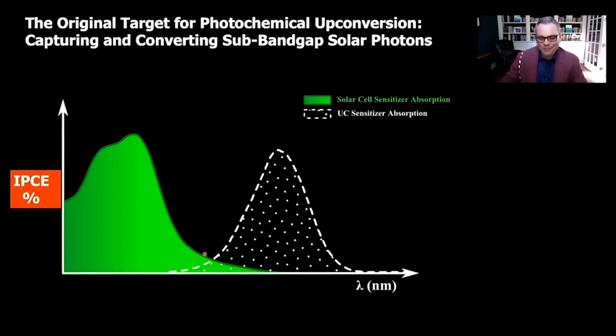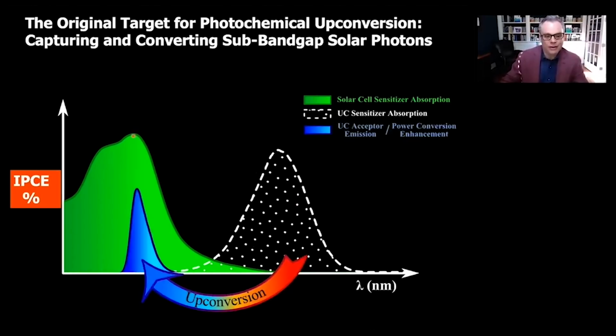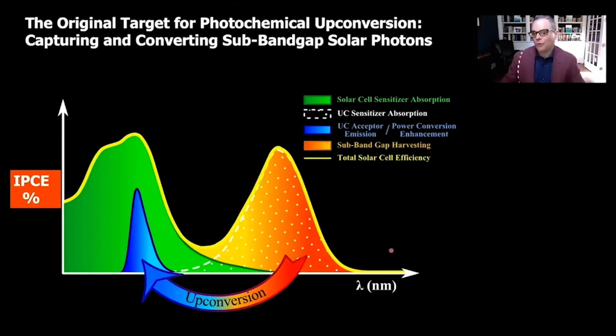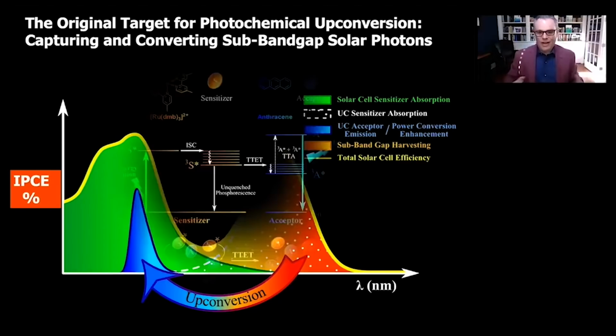So we had this idea, and we never really explored this in a lot of detail. Tim Schmidt has done this really beautifully, so has Ken Hansen. But what we thought at the time was, what if we have a sensitizer that can sensitize the dye-sensitized solar cell? If it has this absorption, and we can induce luminescence into the peak of the IPCE curve in these devices, that would give you power conversion efficiency which integrates more of the solar spectrum. The concept was, can you capture and convert sub-band gap solar photons using this concept? But it required a massive amount of effort to prove you could actually do this for real. That was our whole motivation.